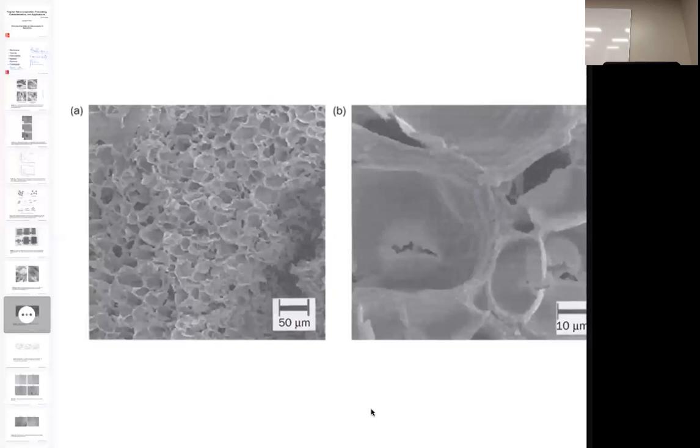And notice the scale here. We're not seeing individual plates. We are seeing aggregates of plates, because this is 10 micrometers, so our individual plates can be on this order of thickness, but a little bit here, we're probably seeing aggregates. And again, if you take this and squish it, it would go over.